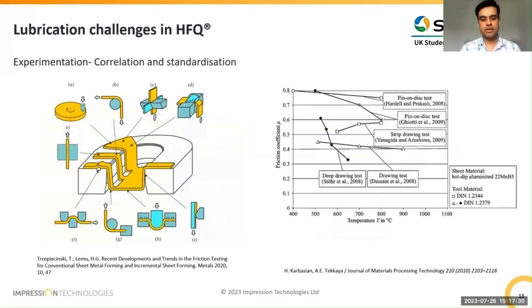Then the other challenge is what experiments to conduct. If you were to look at a part being formed, as you can see here, there are different types of contact. There is bending over tension, there is sliding, there is bending and unbending over a feature, and in the die gap there is ironing. So there are around 8 tests to characterize what is actually going to happen while forming just one part. And all of these are still, let's say, macro scale, and they don't really represent the real production conditions. So which tests to use to quantify what is really going to happen in production is still a problem.